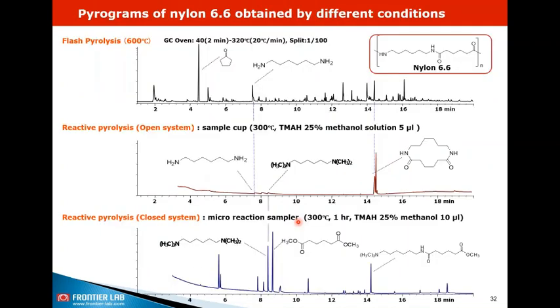So here is the output that you will get when you do the micro reaction, like reactive pyrolysis, for nylon 6,6. As I said, flash pyrolysis cannot give a distinct peak for this monomer. Reactive pyrolysis with the open system gives some peaks, but they are still not prominent. What you see here with the closed system is a more distinct peak, and you also don't have to go to a very high temperature. If you are doing flash pyrolysis, you are going to 600 degrees. Here, the pyrolysis can happen at 300 degrees, and you are able to see the methylated compound of this monomer very distinctly. So this is the advantage of this micro reaction sampler.